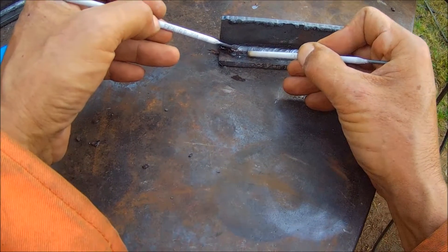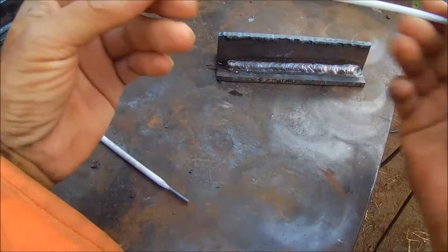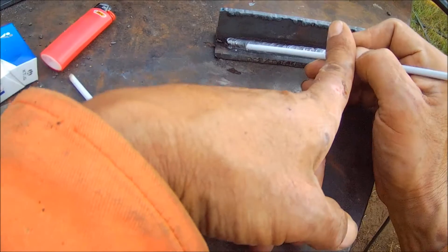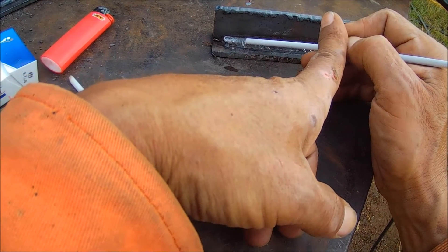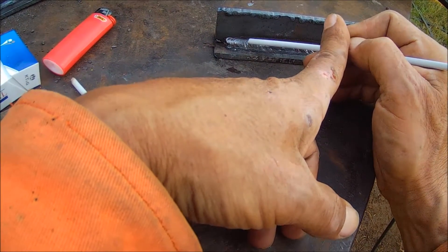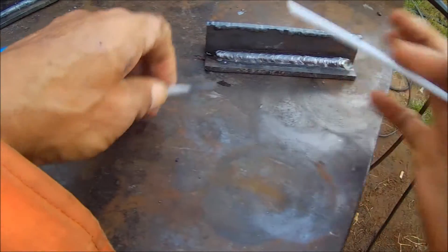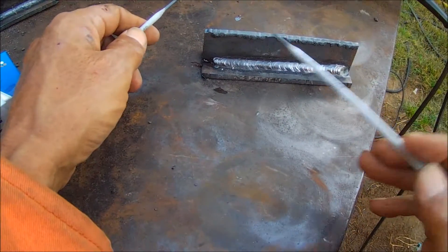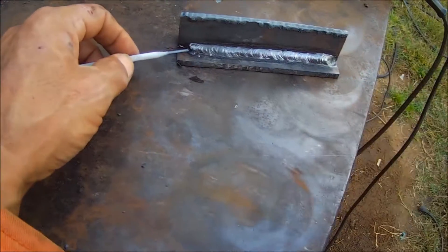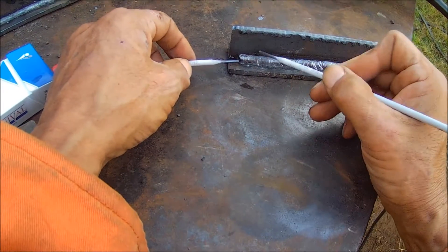It's a stringer. It's twice. Let me see. Here's one that hasn't been burnt down. It's twice the width of the rod. That's about what a stringer ought to be. And this is 3/32". And that's 3/16" plate. So it's a good rod for this size plate. But anyhow.